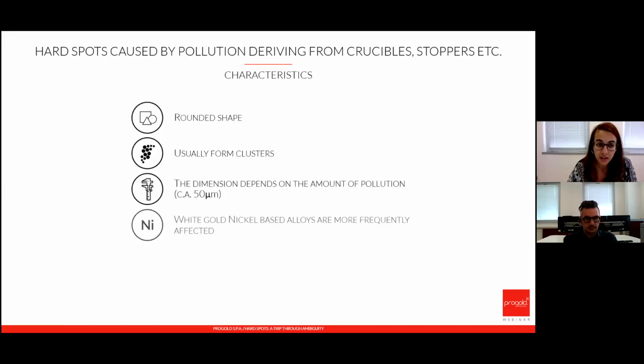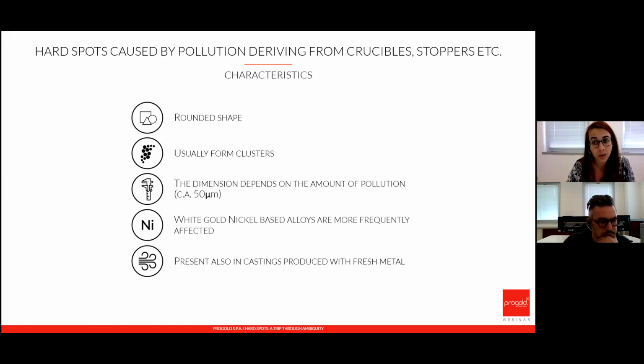Another case of impurities comes from crucible stoppers or any type of material that we can use during the melt. In this case, they tend to be very round. You'll see they're almost a perfect circle. They come in clusters, so you won't see one, you'll see many of them. They tend to be quite big, can be present even if we use fresh alloy, and it happens more often in nickel alloys, but that doesn't mean it cannot happen with other elements as well.